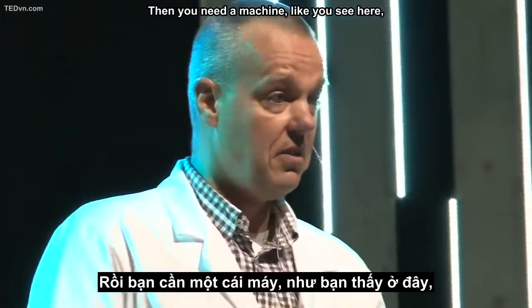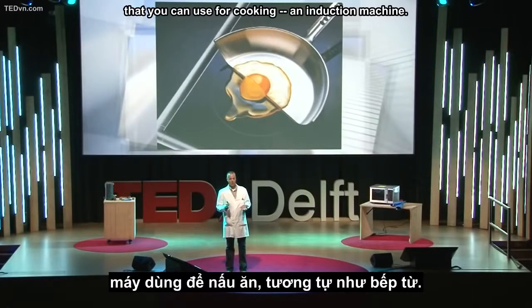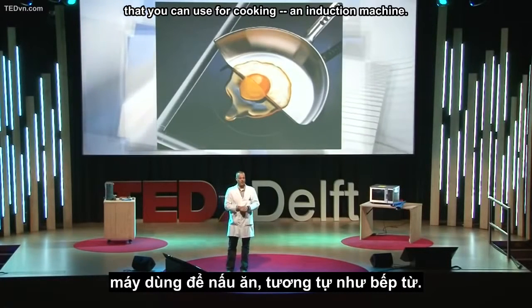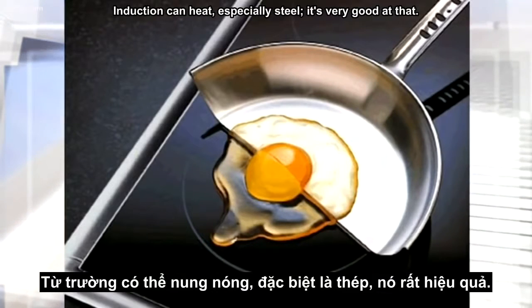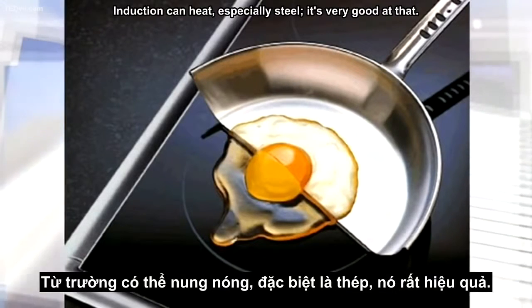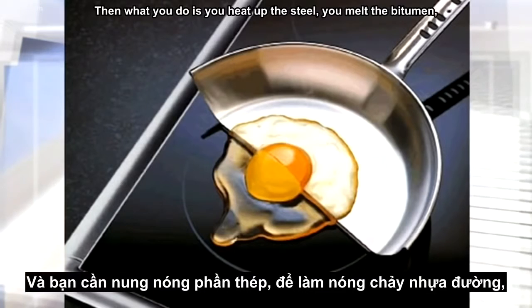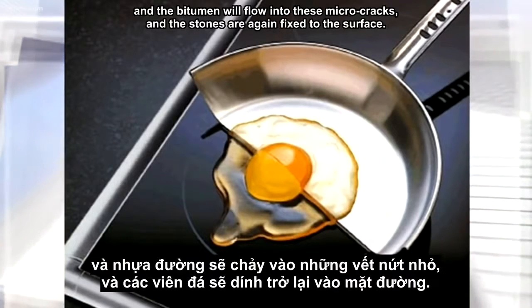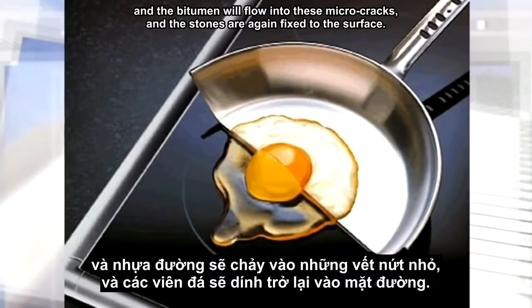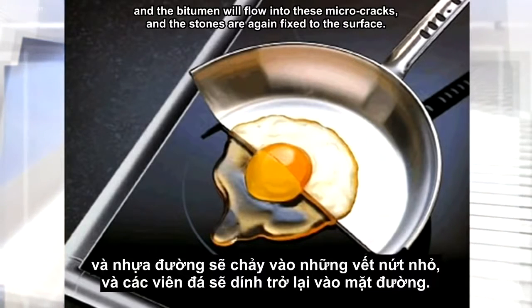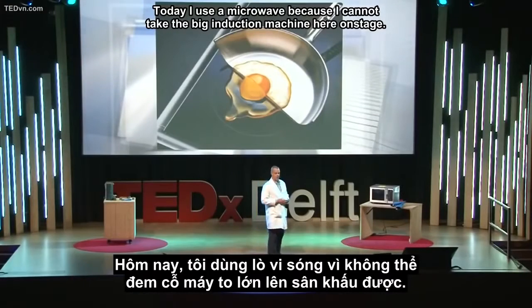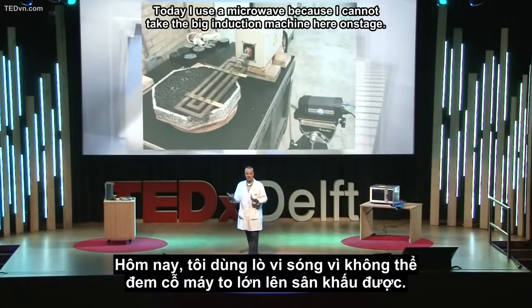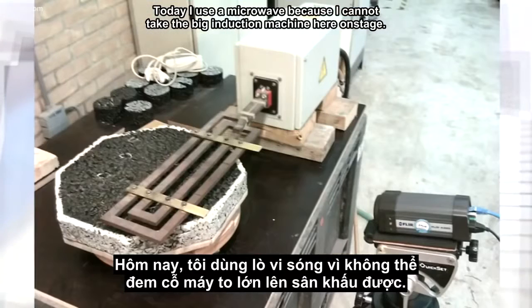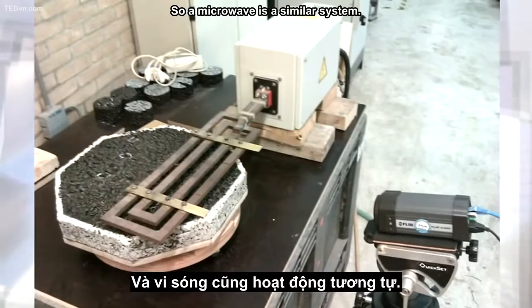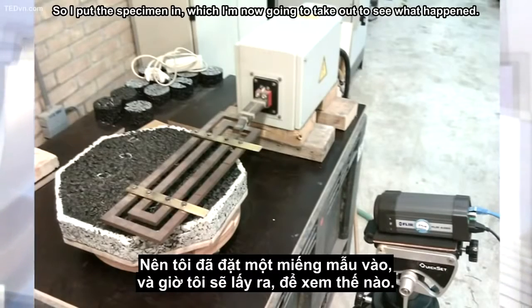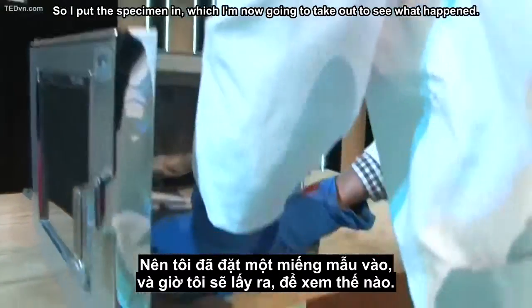Then you need a machine like you see here that you can use for cooking: an induction machine. Induction can heat, especially steel, very well. Then what you do is you heat up the steel, you melt the bitumen, and the bitumen will flow into these micro cracks, and the stones are again fixed to the surface. Today I use a microwave because I cannot take the big induction machine on the stage, so a microwave is a similar system. So I put the specimen in, which I'm now going to take out to see what happened.